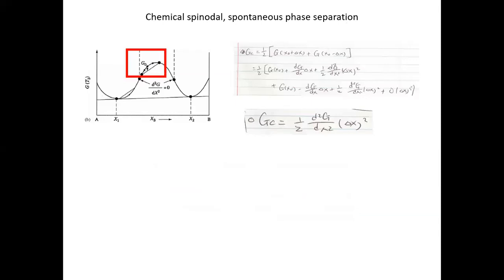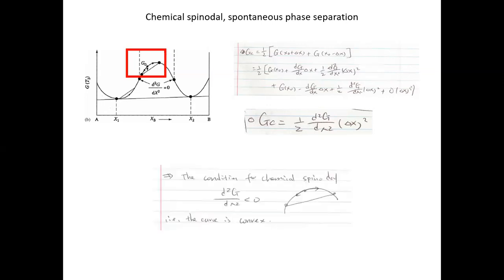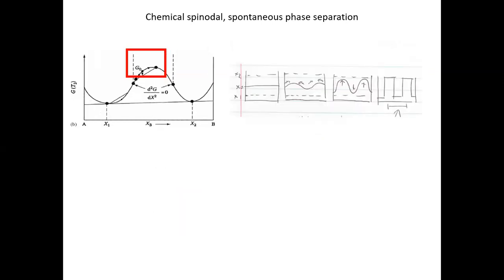But anyway, the driving force part is kind of clear for this one. And now we want to say a few things about the kinetics part, which is very interesting. The reason it is interesting is that if you simply look at what happens during the spinodal decomposition, the normal idea of diffusion does not seem to be working here, in the sense that you start with an initial homogeneous mixture. But in here, there's no structure change. Everything's the same structure. So you're just dealing with diffusion alone.